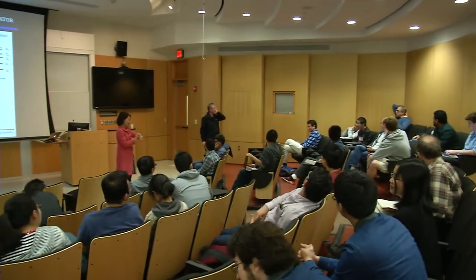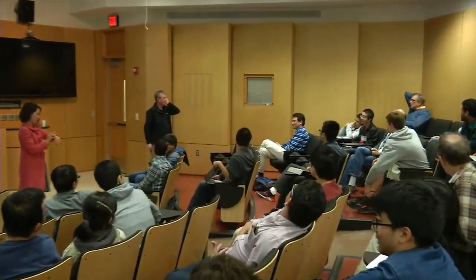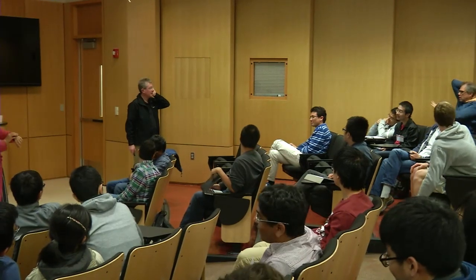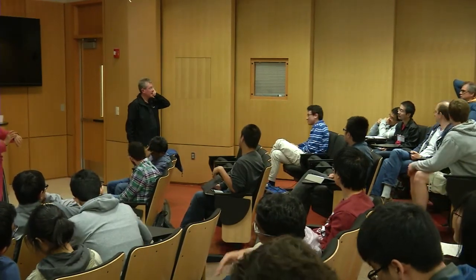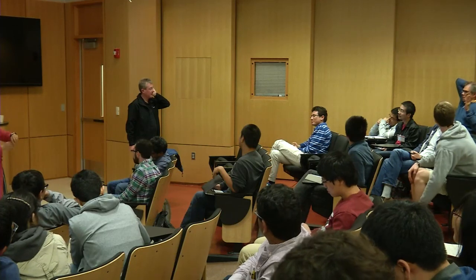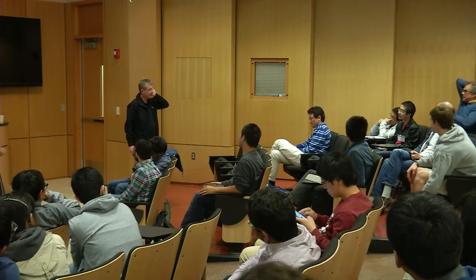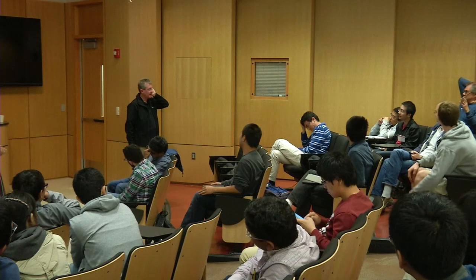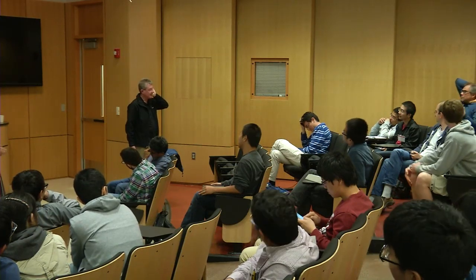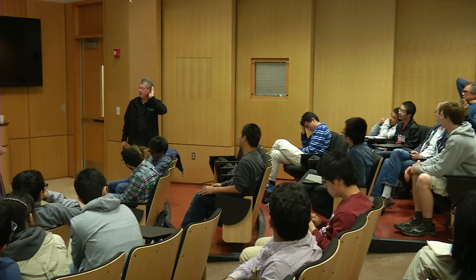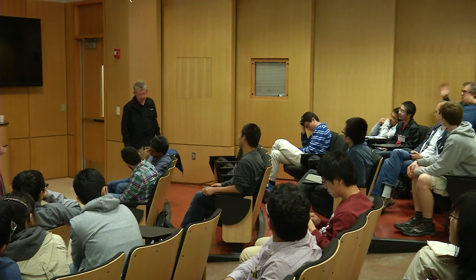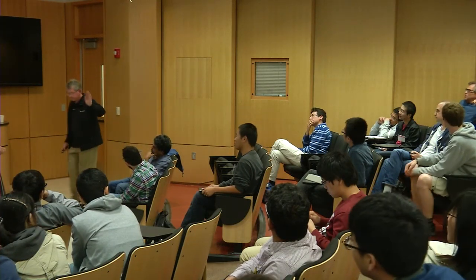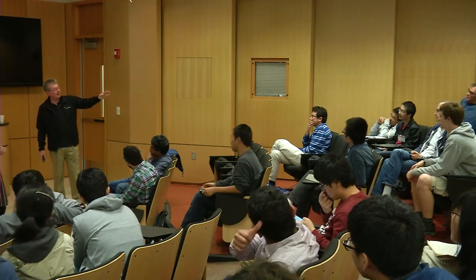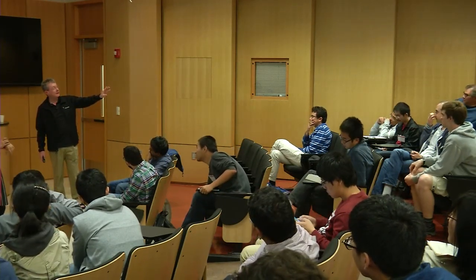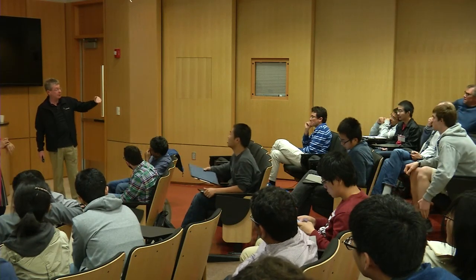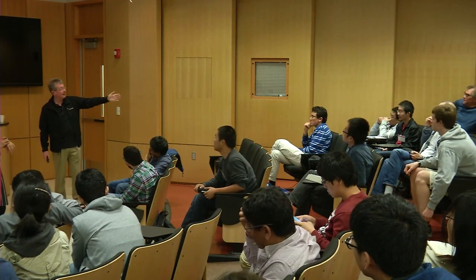What you are saying is that the Z factor differs on different orbitals. People like Laad and others who were doing calculations of self-energies were saying, yes, of course, there are K-dependent self-energies, not omega-dependent, that produce different Z factors on different orbitals. In terms of their calculations, it has nothing to do with the Mott phase. It's just a strongly interacting system which has different Z factors on different orbitals. I think you're right. The literature in that field uses the phrase orbital selective Mott phase throughout, and maybe that phrase needs to be deleted.